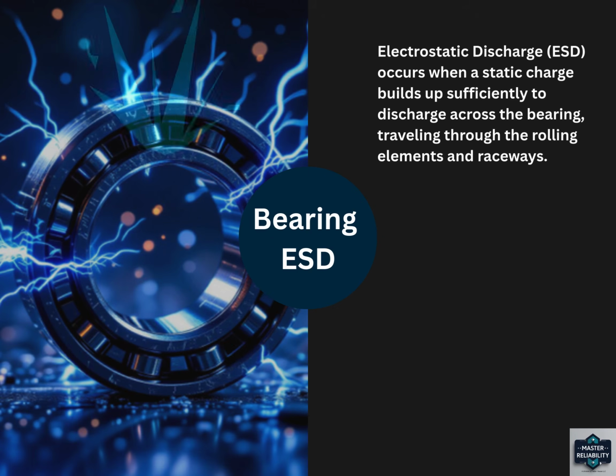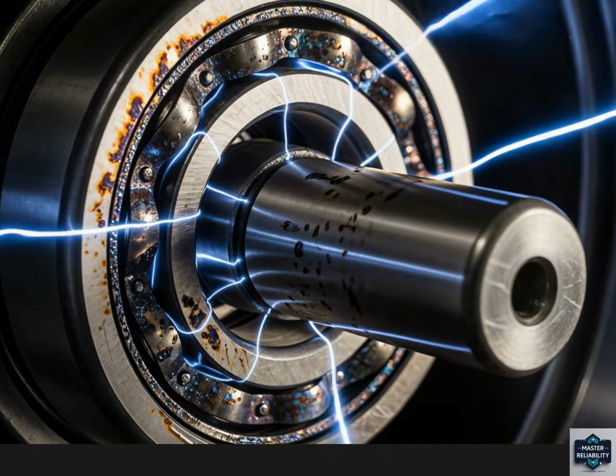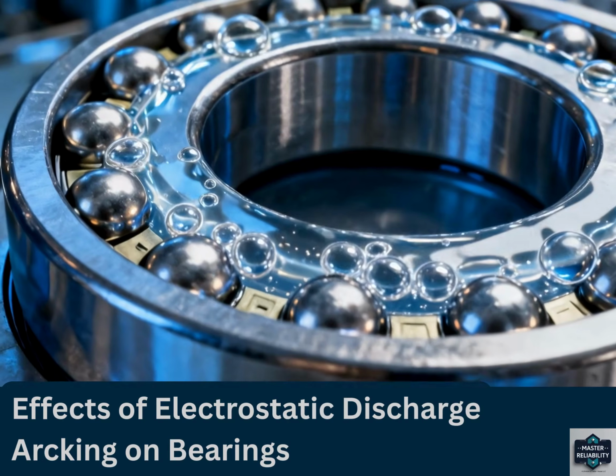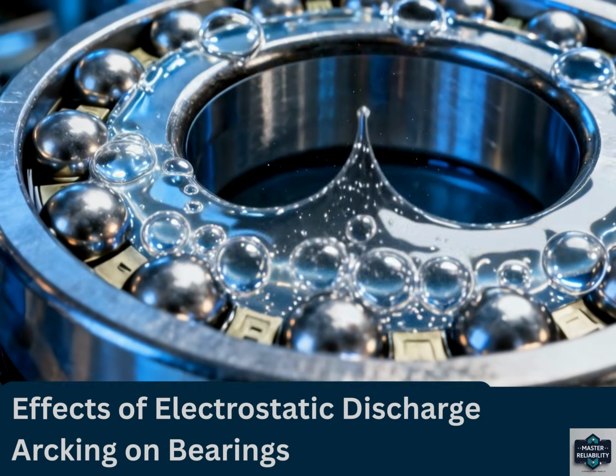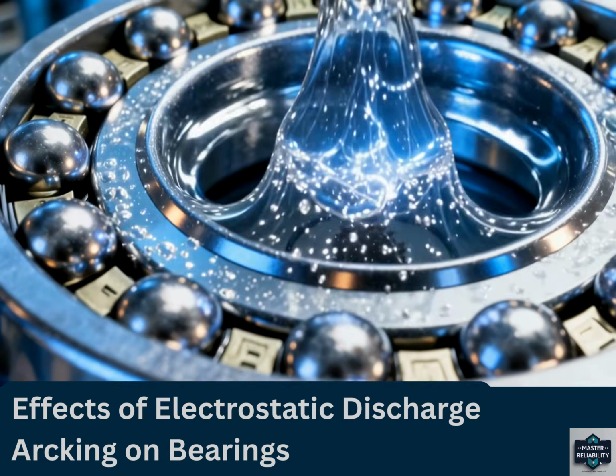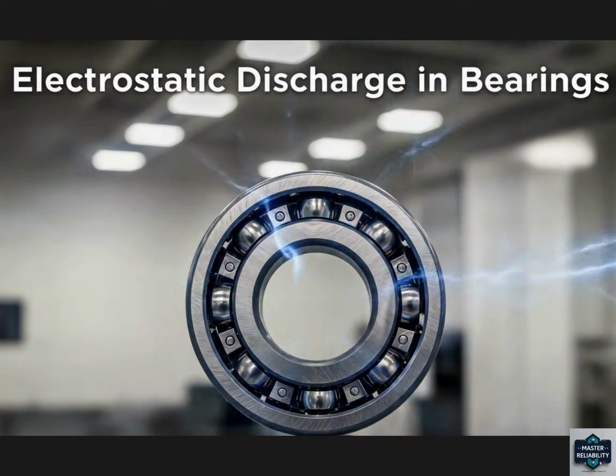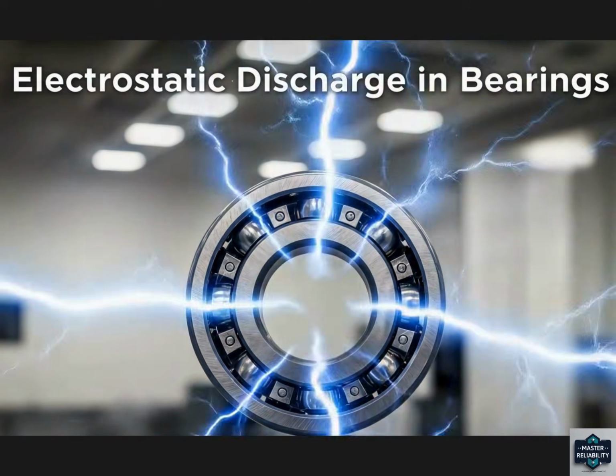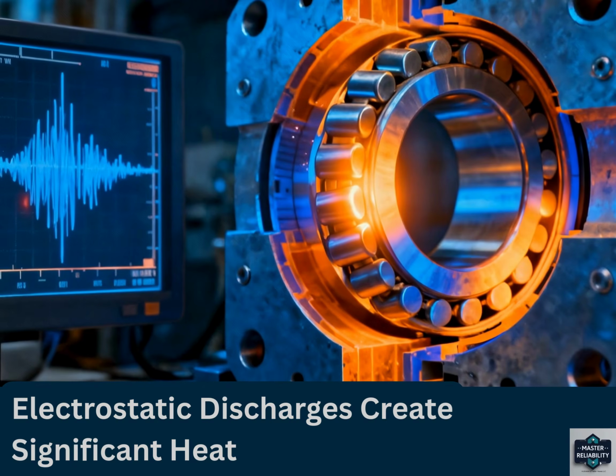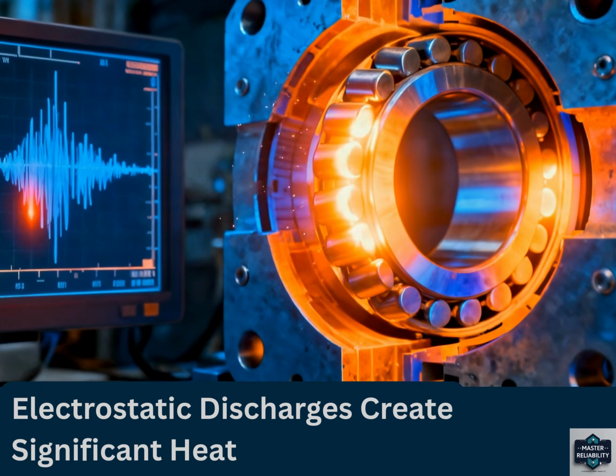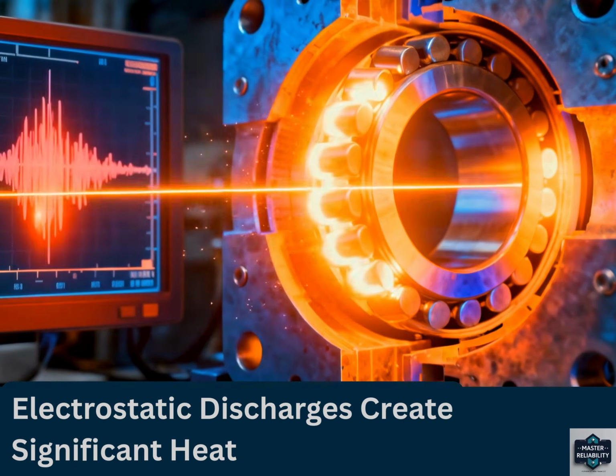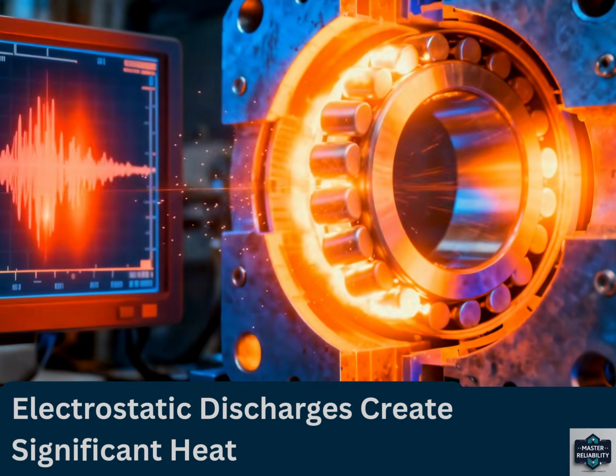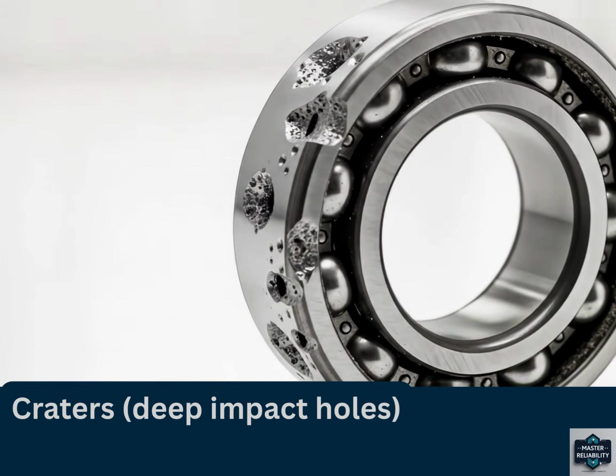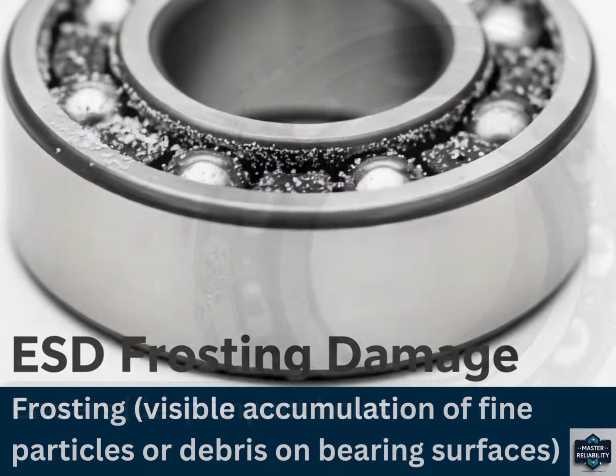Electrostatic discharge, or ESD, occurs when a static electrical charge builds up and discharges across a bearing, traveling through the rolling elements and raceways. This discharge creates microscopic electrical arcs at contact points. These arcs generate intense localized heat that briefly melts the metal surface. As the metal rapidly cools, it forms characteristic damage features: craters, which are deep impact holes, frosting, a visible accumulation